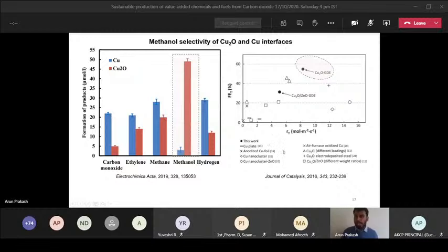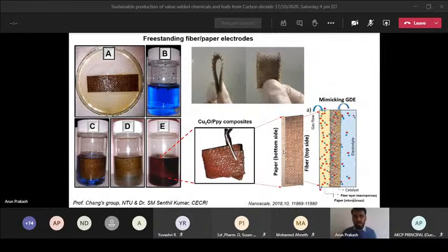And in our recent work, which we did in 2018 at National Taiwan University, we tried to prepare some flexible freestanding paper electrodes. We want to introduce some nitrogen sites in our catalyst, because nitrogen-containing sites can increase the CO2 local concentration. So this is a commercial paper, very cheap, like normal fiber paper, and we soak it in an organic compound like pyrrole, and introduce this into a copper solution. Because of the metal to ligand charge transfer, from copper to pyrrole, polymerization of pyrrole will happen, and it will form polypyrrole. And polypyrrole has a nitrogen attached to the 5-membered ring, and this is good for CO2 reduction.